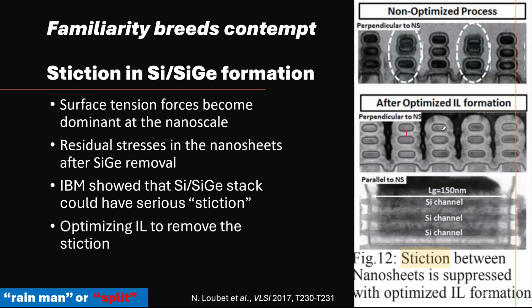What's the distance between here? It's only 10 to 15 nanometer. You cannot go over 15, going over 15 is useless. Below 10, there's no process. So between 10 to 15, such a small separation. And these are all highly strained initially, so it will be easy to stick together. There are serious stictions. There's a residual stress everywhere after SiGe removal.